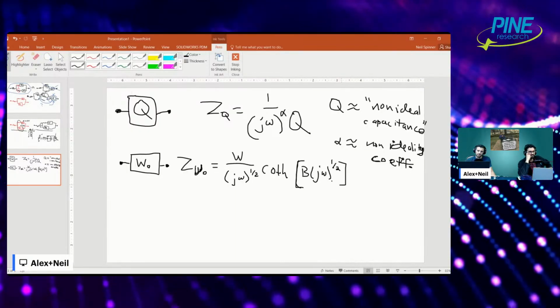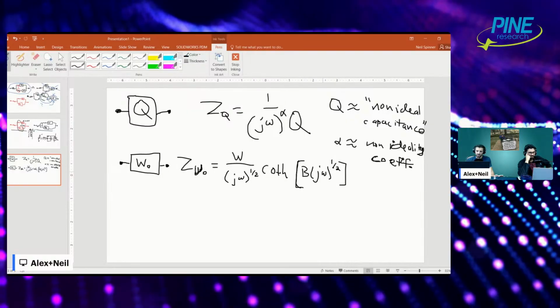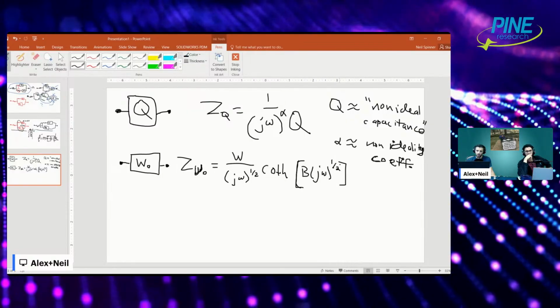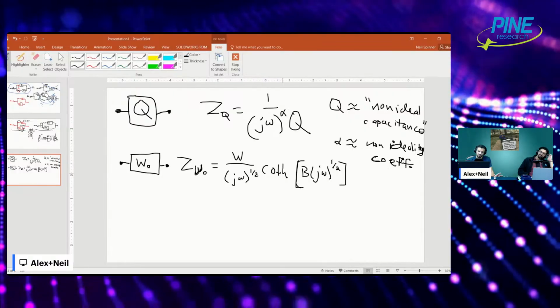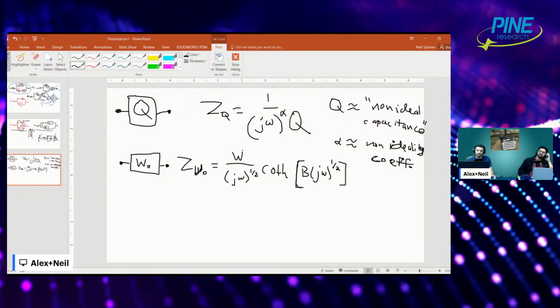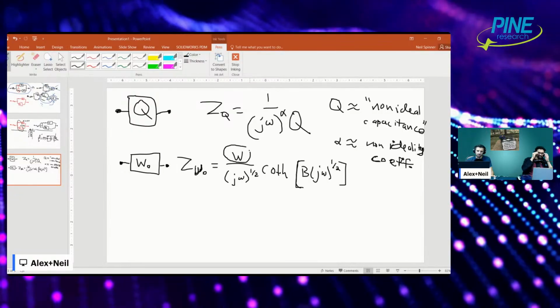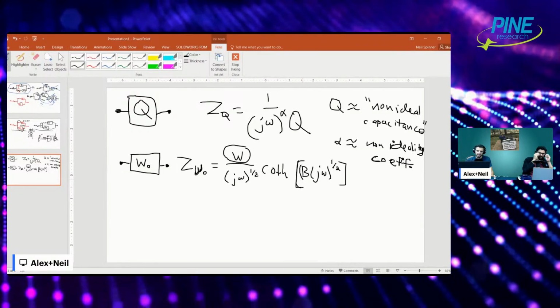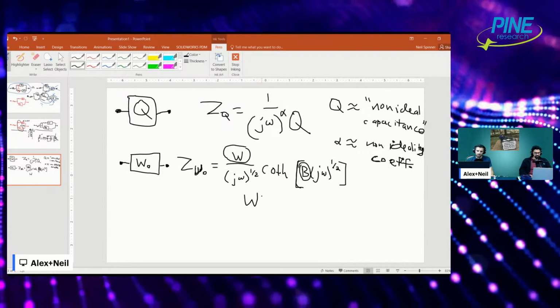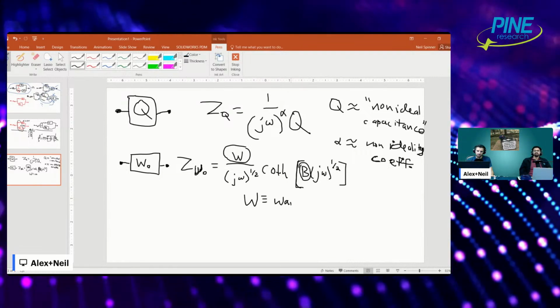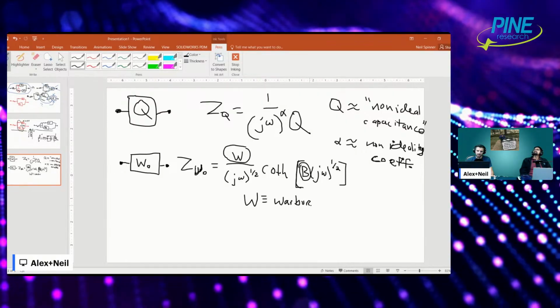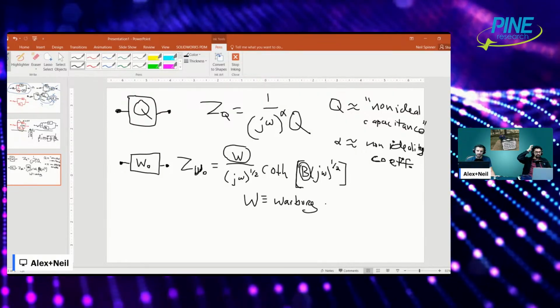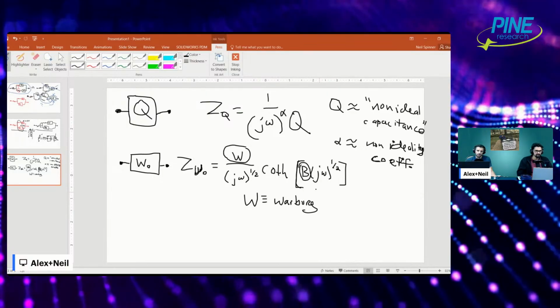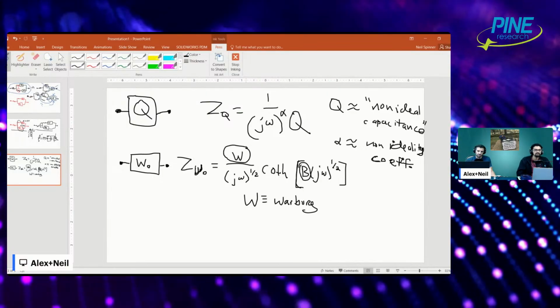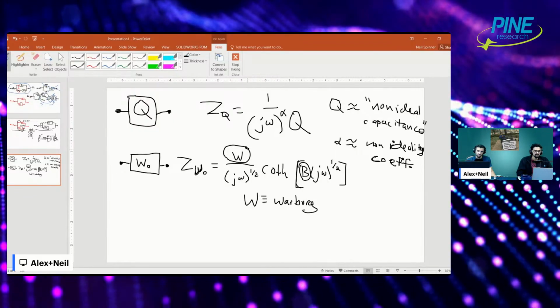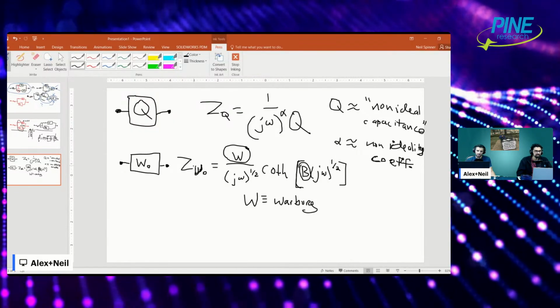So don't worry too much about the math. I know hyperbolic cotangent, it's like whatever, and there's an imaginary figure to the square root power within a hyperbolic cotangent. The math gets a little hairy. Don't worry about it. The point here is that you have, again, two parameters. You have W, but now you have B. And so W is the Warburg constant, which is, as I showed before in my other slide, basically proportionate to the diffusion coefficient. It's related to the impedance of the diffusion, and here you can see it's directly proportionate to ZW, right?